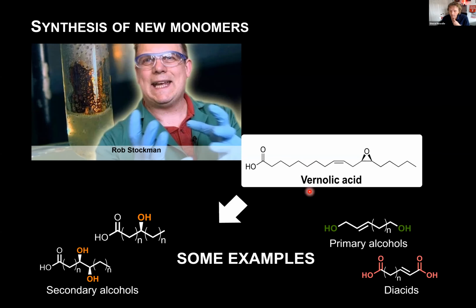What Rob showed was that we could take this really nice molecule, which actually does polymerize a little bit on its own, but not really effectively. We did a little bit of simple chemistry on it, popped open this epoxide here, and made a single alcohol group — we made a diol. So you can see here we've got two different molecules in one quite easy step from vernolic acid.